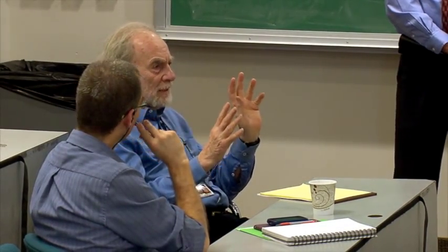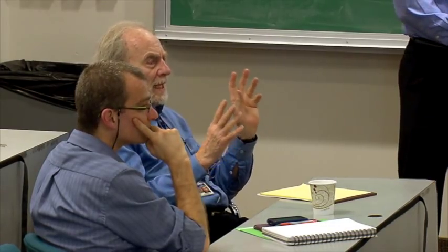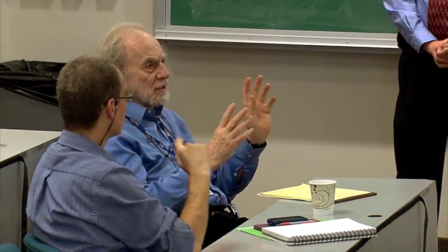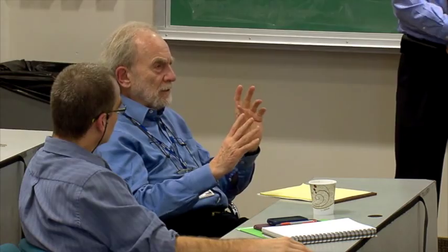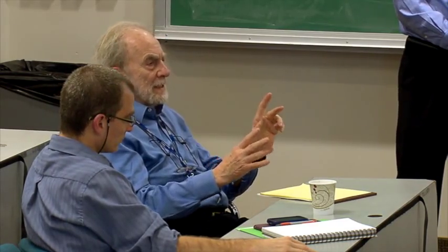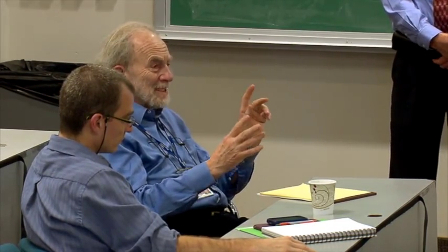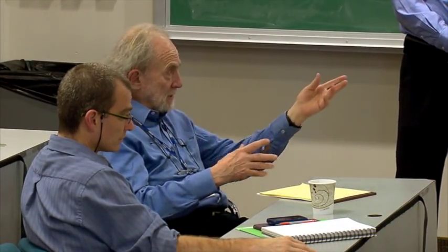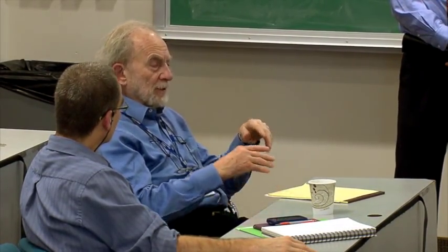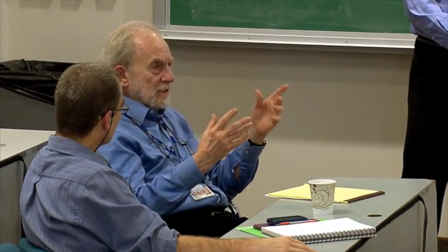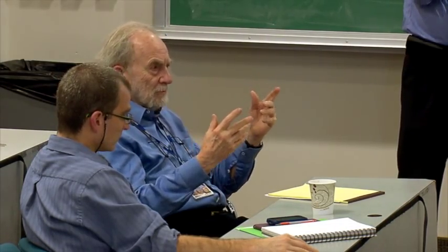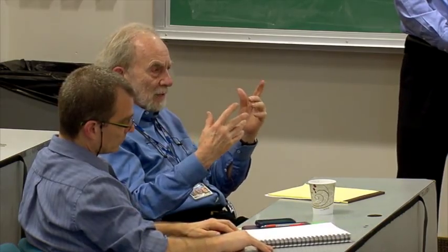It's all due to grain boundary diffusion. And the mobility, sintering, creep, any property you'd like to think about for alumina is due to grain boundary diffusion, and it's not a point defect mechanism. It is some collective mechanism, which I think is a disconnection. But there nevertheless are vacancies or interstitials that have to be involved to allow these disconnections to nucleate and propagate.